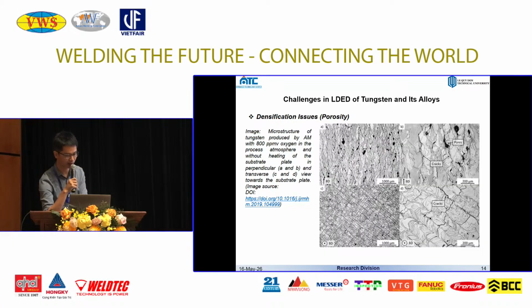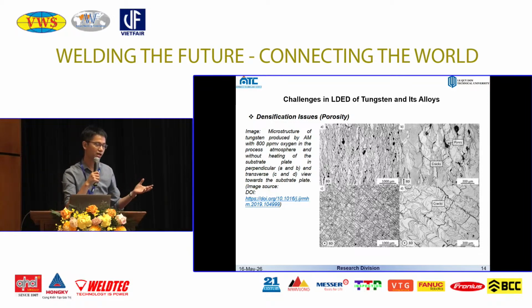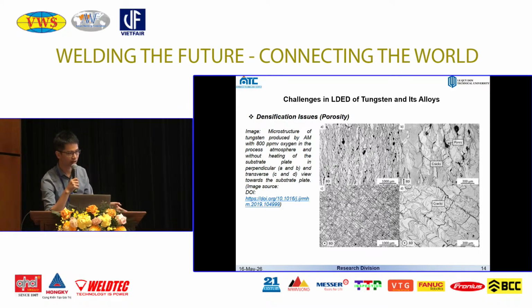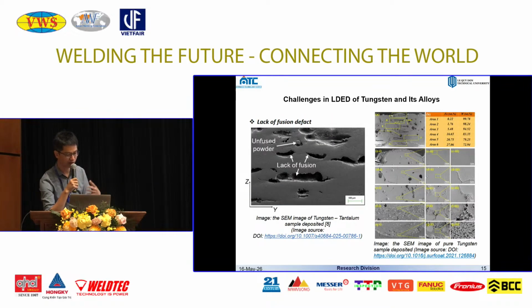The next challenge is the densification issue. Achieving full density is very difficult because of the high melting point and low laser absorption. For tungsten, the laser absorption with a fiber laser is pretty low, lower than 30%, so it requires very high energy density, which can cause keyholing or evaporation of the material. Third, we face defects or incomplete melting. Lack of fusion in LDED of tungsten is mainly caused by insufficient melting or poor wetting between the deposited layers.